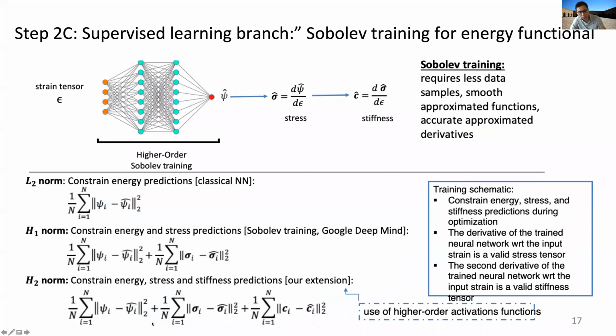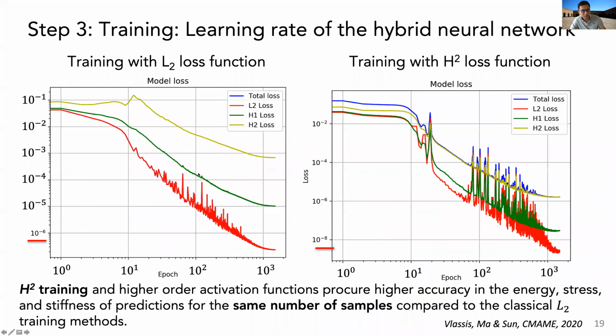in which we train not only on the L2 norm but on the Sobolev norm in the Sobolev space. You can see here, this is quite interesting: in the classical way, we train the loss function using the mean square error, and we get the pattern on the left. Notice the values here, 10 to the minus 6 to 10 to the minus something. If you train with the H2 norm, the interesting thing is that not only is the H2 norm doing better, but even the L2 norm is doing better. So if you optimize the L2 norm and then measure how good it is using the L2 norm, the H2 norm training actually performs better than the L2 training, even when measured against L2 performance.